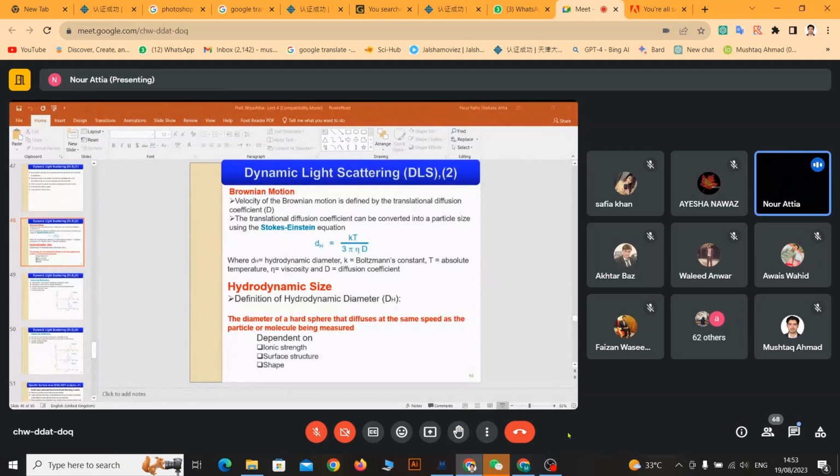You will use silver or gold as an anti-cancer agent, so you will inject it in a solution to go inside your serum. So the motion will be governed by this hydrodynamic particle size, not the one you see in the TEM. So if you measure TEM and find your sample is 50, and you measure DLS and the size is 150 or 120, don't be confused. This is logical because you have a capping agent layer, then a hydration layer. That's why we say it's a hydrodynamic size. Is this clear? Somebody reply to me. Yes, sir, it is clear.